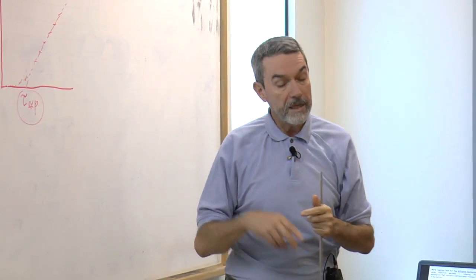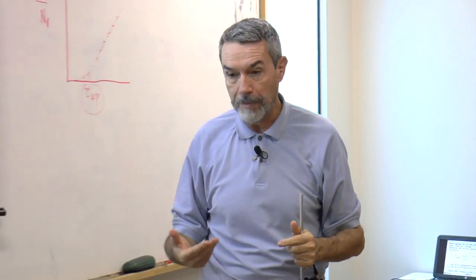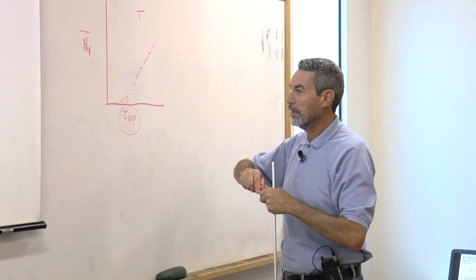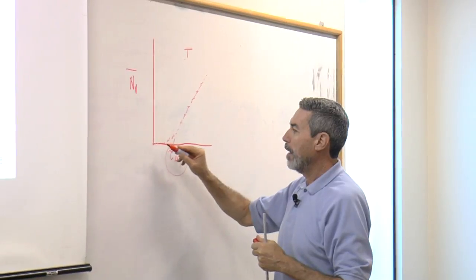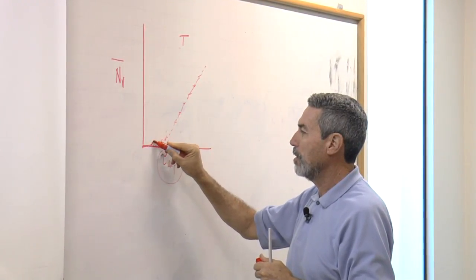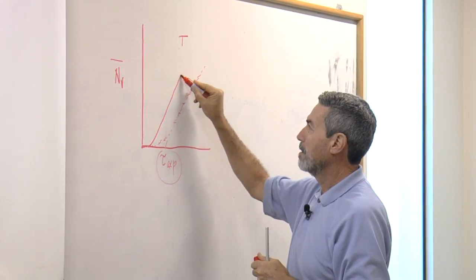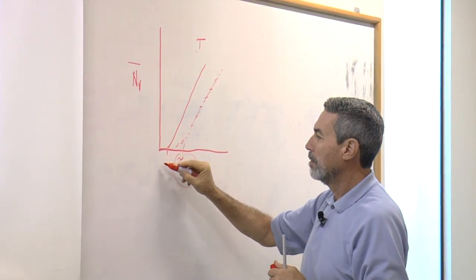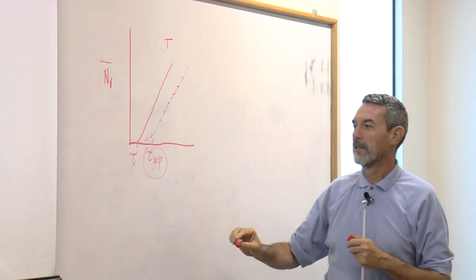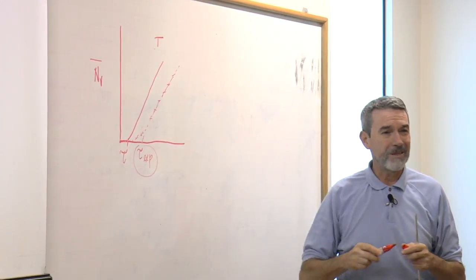And this second heat treatment brings important errors here in such a way that the real curve, if we are able to do a single stage heat treatment, would be like this. So the real tau is smaller than the experimental tau.